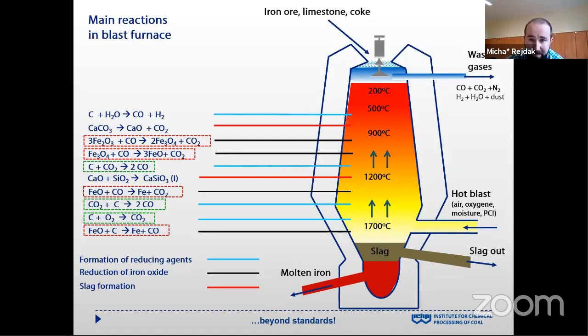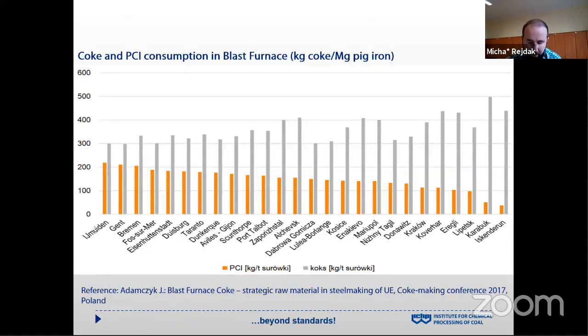Due to the difference in density, because apart from iron, of course, some slag is created during the blast furnace process, the liquid iron flows to the bottom of the furnace, while the slag is on its surface, from where it is drained out. In modern blast furnaces, in addition to coke, alternative fuels such as pulverized coal or natural gas are used as a heat source. Moreover, modern furnaces are taller and have a greater working volume, which is related to the higher mass of the input material. Therefore, the physical role of coke is increasing in importance. That is to say, providing a grid for the column of material and the gas permeability of the bed.